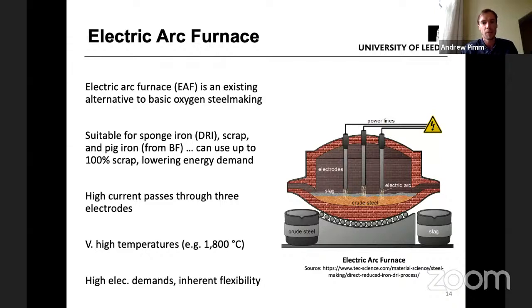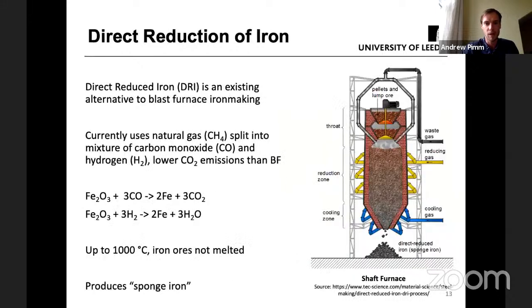And then another option for steel making, I mentioned before, is the electric arc furnace. This can be used with sponge iron, that DRI, as I just mentioned, which comes from a DRI furnace. It can be used with very high levels of scrap. It could also be used with pig iron from a blast furnace. And as I said, you can use very high levels of scrap in an electric arc furnace, which is great for lowering energy demand. You pass a high current through 3 electrodes, reach very high temperatures, around almost 2000 degrees C, and you have a real inherent flexibility there. As I understand it, there's also some flexibility in going back into the operation of a DRI furnace, much more so than a blast furnace.